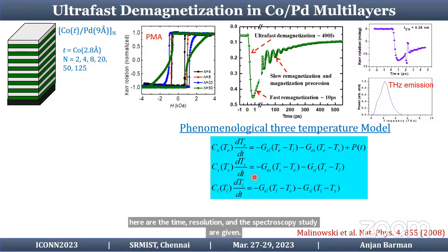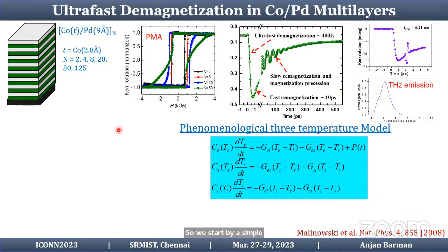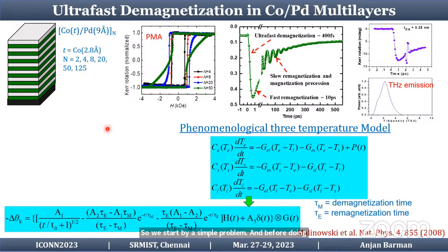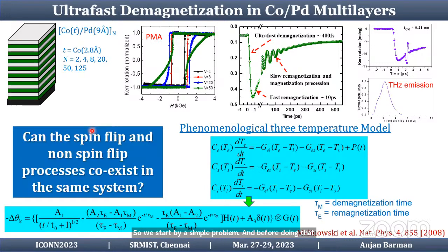So we start with a simple problem, and before doing that, we try to motivate ourselves by saying that, as we already said, there are various mechanisms which govern ultrafast demagnetization, and one of them is the spin flip scattering process, and another is thermal transport or spin transport, which is a non-spin flip scattering process. Our goal is to understand whether these two processes can coexist in the same system, and if so, can we control them together? So for that, we took a system called a cobalt palladium multilayer, which shows a perpendicular magnetic anisotropy.